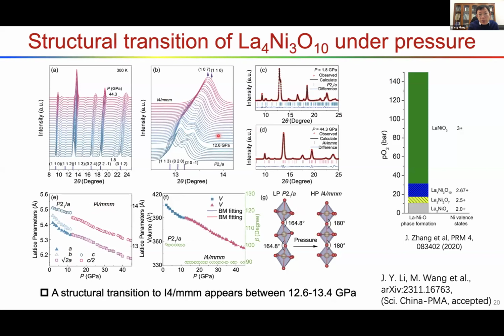So I think the reason for the difference in volume fraction for the two systems may be that the 4-3-10 system is easier to grow because there is a larger oxygen window for this compound. But the 3-7 compound is more difficult. The oxygen pressure window is narrower. It's not very stable. But once we get this sample, it's stable in the atmosphere environment.